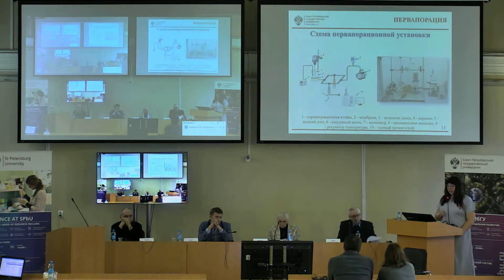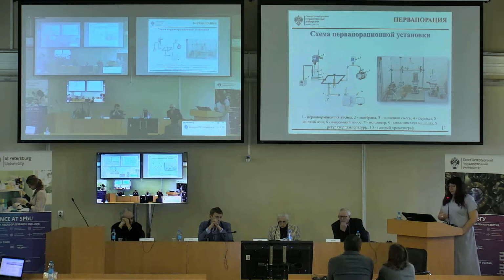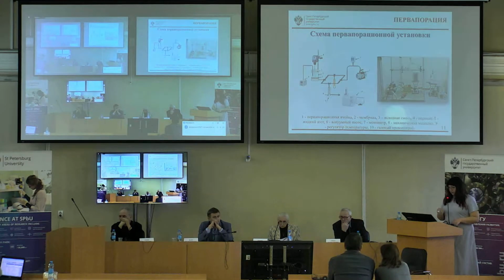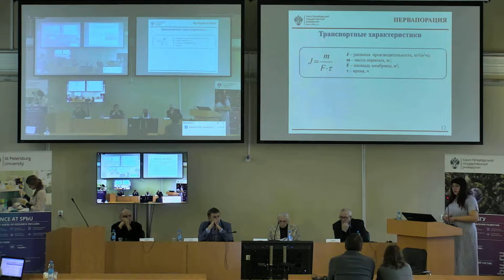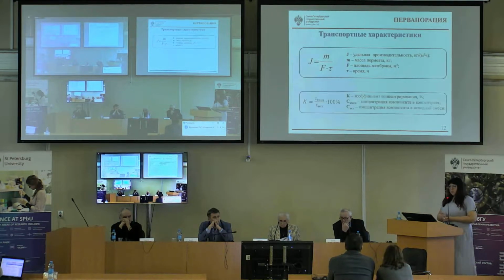A membrane is inserted into the pervaporation cell, onto which the separation mixture is poured. Pressure is created under the membrane using a vacuum pump. The components that have passed through the membrane are condensed in a trap cooled with liquid nitrogen. The composition of the permeate was determined by gas chromatographic analysis.